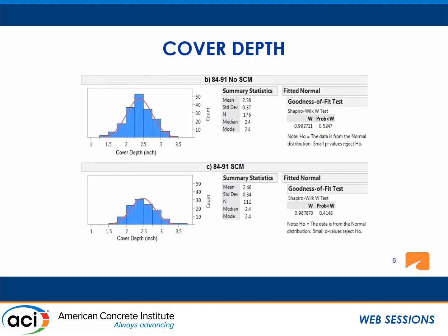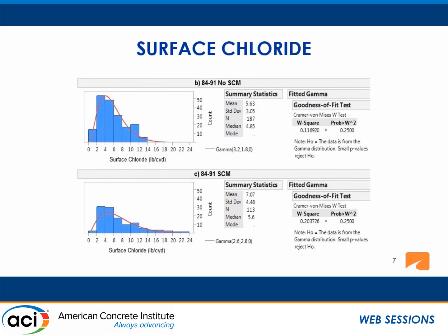Here are two distributions for the two groups of bridges. The one on the top is the one with plain concrete, and the one on the bottom with the supplementary cementitious materials. They look pretty much like normal distributions, and the cover depths are pretty much in the same range. And these are the distributions for the surface chloride concentrations, and they looked about like gamma distributions, and they were almost in the same range as well.